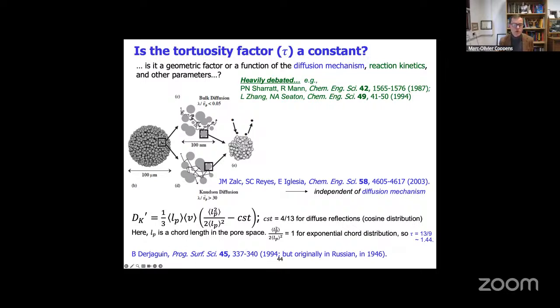But look here in English also, in this paper in Progress in Surface Science in '94, there's an elegant theory he derived on the basis of chord length distributions. And he showed really simply that if you have diffuse reflections, so a cosine distribution on the walls, which is also what Knudsen assumed, and you have, say, an exponential chord distribution, which often happens, by the way, like in this model of Reyes and Iglesias, then the tortuosity veers towards a constant. It becomes approximately 1.44. That's really an analytical model they were able to derive.